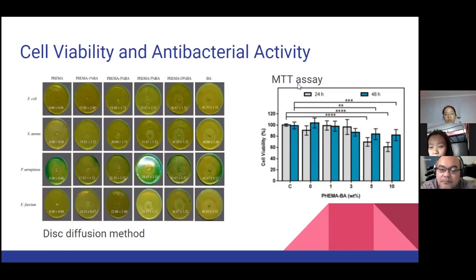And this is the cell viability. It was tested using MTT assay, and it could be seen here that there is no difference in the cell viability of the PHEMA-BA, but there is a decrease of cell viability in the 5% and 10%. This means that only the 1 and 3% is eligible to be used in vivo.